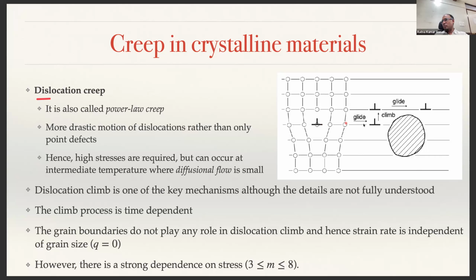If your dislocation is on one slip plane and goes from this slip plane to this slip plane, this is what is called climb. If the dislocation is moving on the same slip plane, that is called glide. If it is moving from one slip plane to another slip plane, that is called climb. This climb is more energetically strenuous, which means it requires more energy, and this can actually take place during this mechanism called dislocation creep. In this particular scenario, the grain boundaries do not play any role, and hence q will become equal to 0 and the m value will be from 3 to 8.